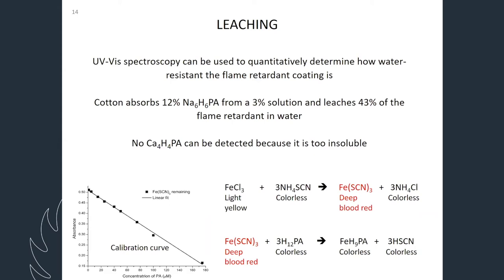Next question: when we made the samples, are they stable? If we put the samples in aqueous solution, for example, if we make a cloth out of it, will it be there if it gets under rain or if it gets washed? To know that, we used UV visible spectroscopy. What we did, as you see in the bottom part, is take ferric chloride solution and add ammonium thiocyanate solution to it. Both are very common reagents in chemistry labs. Then iron forms a deep red color complex, which can be easily detected by UV visible spectroscopy.